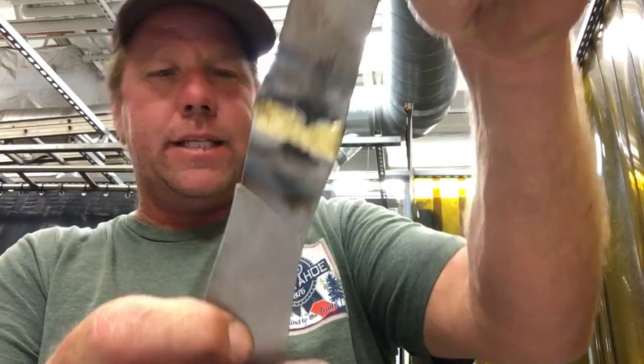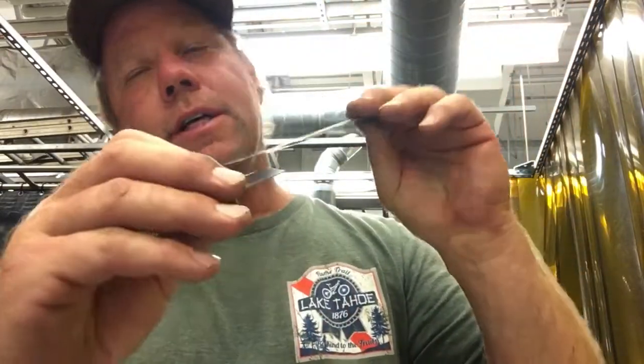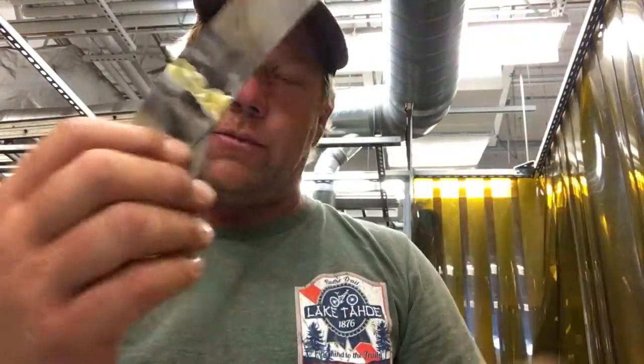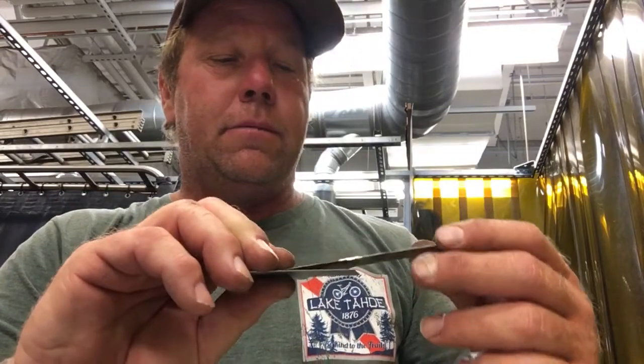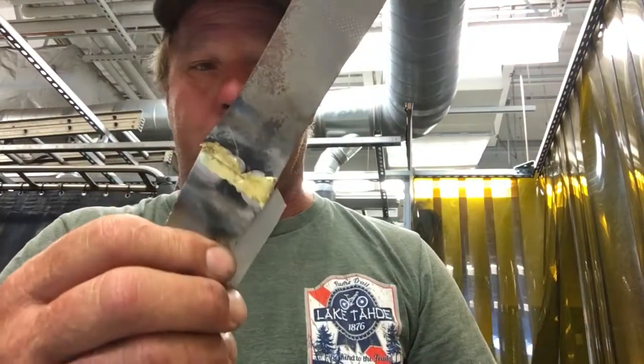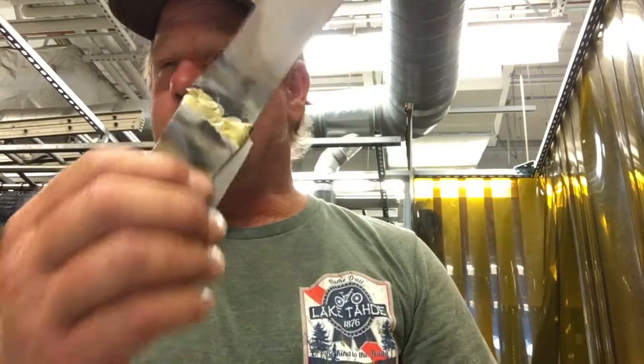And why does brazing do better than the others? When you get into thin material, brazing does really good because brazing does not melt the base material, and that is key. Don't melt the base material, you don't make any martensite formations, you don't have that heat affected zone, doesn't make those tears hopefully, and that's where you see brazing's very, very good on thin materials.